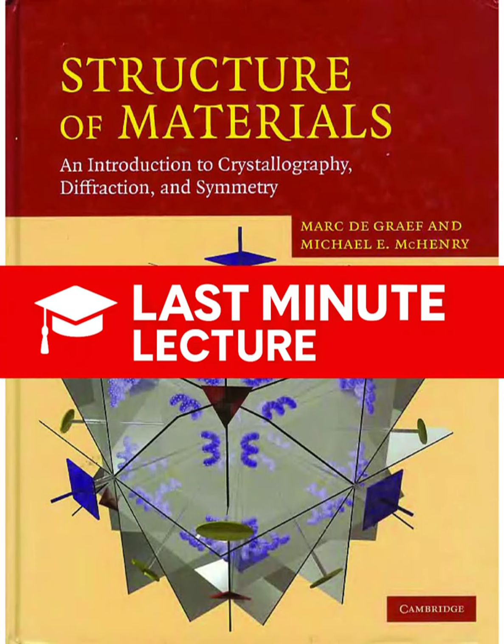The measurable intensity, IHKL, is proportional to the square of the magnitude of that structure factor, so proportional to the absolute value of FHKL squared. Since FHKL is a complex number, its magnitude squared is found by multiplying FHKL by its complex conjugate F star. Correct. And it's this squaring process, this measurement of only the magnitude, that's the reason we lose all the phase information of the individual atoms. That's a fact we're going to come back to later when we discuss Friedel's law.